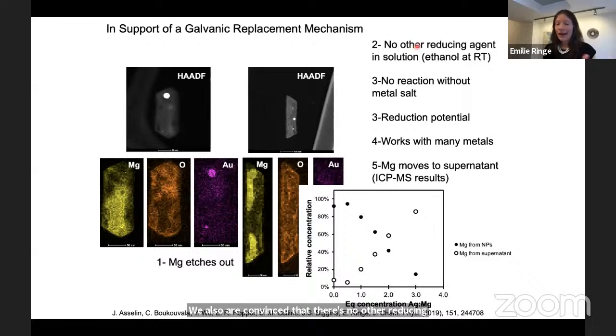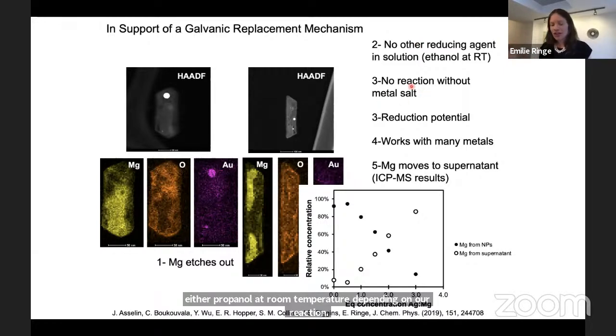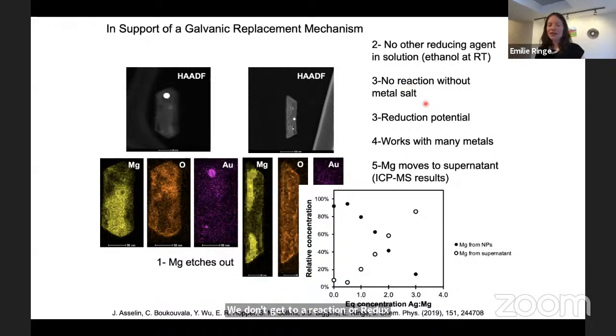This is ethanol at room temperature or isopropanol at room temperature, depending on our reaction. We don't get a reaction or reduction of our magnesium if you don't put the metal salt. The thermodynamics tells us it works. It works with basically any metal we want to try. And we can track actually where the magnesium goes from the centrifugation pellet to the supernatant as the reaction goes. That tells us that indeed it goes from magnesium metal to magnesium aqueous.